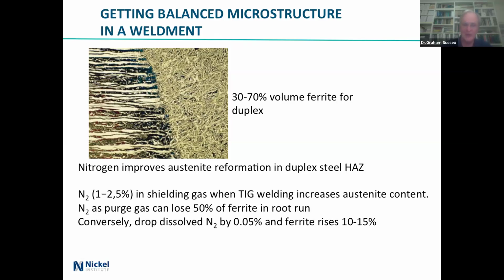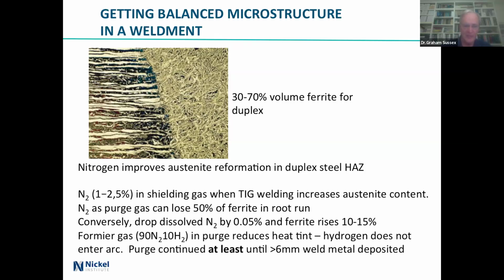But that's usually the person who's actually the welding engineer who's done the design. And the forming gas reduces the heat tint. The hydrogen won't get into the arc because it's on the inside, and continue the purge until you've got at least 6 millimeters of the weld deposited if you're talking about a thick material. I have told the story to people of some people making pipework for desalination plants, good thick stuff. And they did the first 2 passes and then turned off the purge gas, and the inside of the things were absolutely black, which was lots and lots of cleaning.